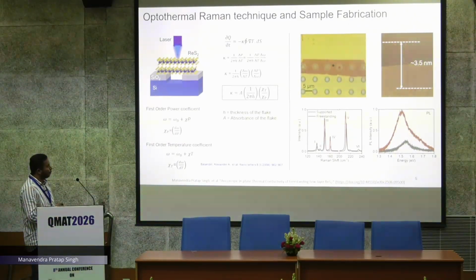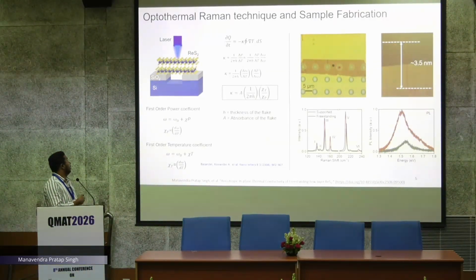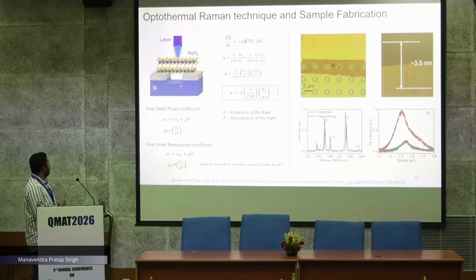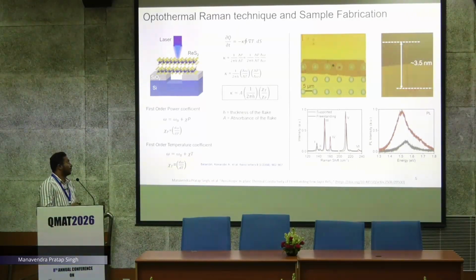I will show the sample fabrication. The method is simple to calculate the thermal conductivity. This is a sample schematic, how we make the sample. There is SiO2/Si, then we etch using RIE, then put ReS2 on that. To calculate the thermal conductivity of the material, we just calculate the power coefficient and temperature coefficient in the suspended region. Then we use this formula given by Balandin, a very well known formula for the thermal conductivity of 2D materials using Raman thermometry. We have used this procedure to calculate the anisotropic thermal conductivities.